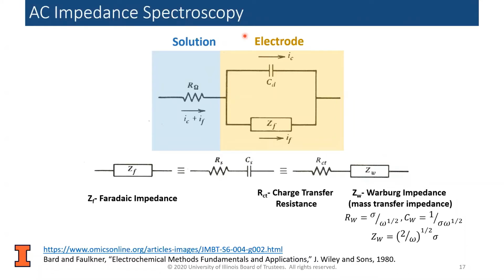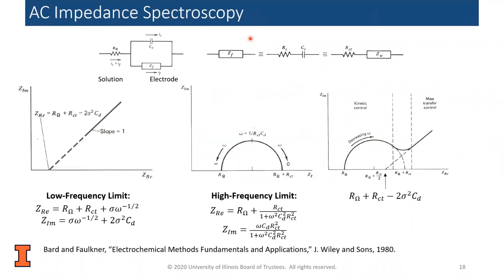So how do we use this? If one knows the circuit diagram, one can actually solve the equations for that and use that to quantitatively model the spectra that you get. Sometimes, when we look at the electrochemistry at the low frequency limit, we'll get a 45-degree angle relative to the real and the imaginary axes of the impedance plane. And this indicates the increased frequency right here. At the higher frequency limit, we'll see a spectrum that looks like this. It's just a semicircle. And then in most cases, you'll see both parts of the spectrum because we'll scan from low to high frequencies. Then you'll get the semicircle.